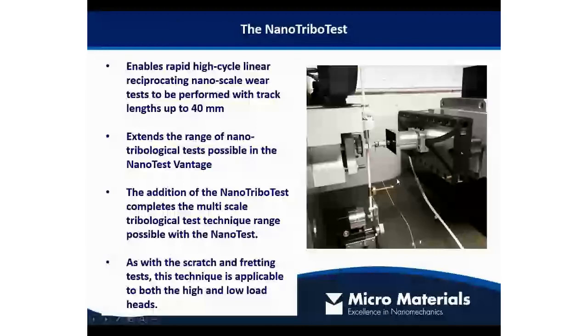The nano-tribo test, as with all of these techniques, utilizes the same nanotest loading head as all of our testing methodologies. Essentially, it's a linear reciprocating tribometer test. The sample is oscillated backwards and forwards over a user-specified distance, which can be up to 40 millimeters. Friction's measured continuously, and we can measure depth data as well. We can change the contact geometry. It's very flexible. In this case, we've got a very big 6 millimeter diameter ball in place.